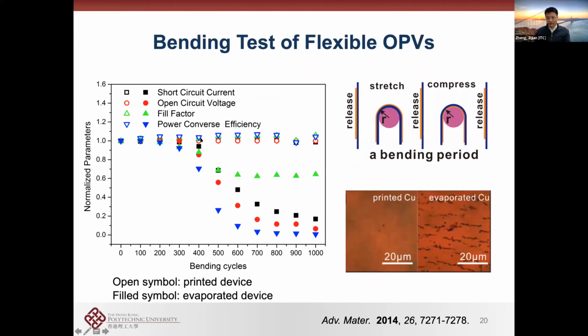But the key thing is the flexibility is way better. So we bend the device, one with the printed electrode, one with the evaporated electrode. For the one with the printed electrode, there's no problem at all if you bend it 1,000 times. But for the one with the evaporated electrode, they actually fail after like 400 or 500 times, right? The entire device goes down and dies immediately. And the reason is the formation of cracks. So the bendability of the device is way better, and the performance was not sacrificed. That's the key message right here.